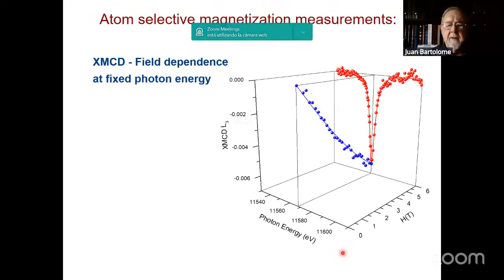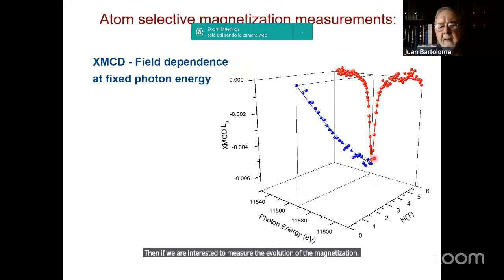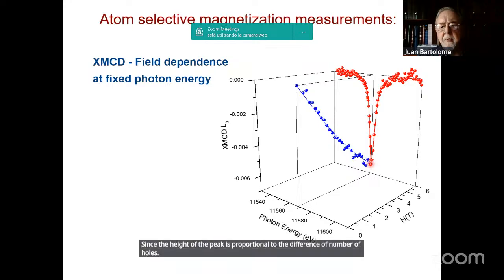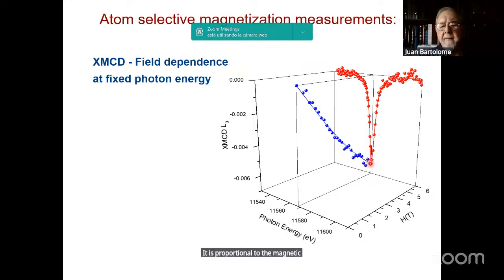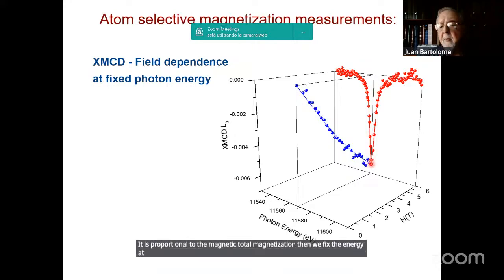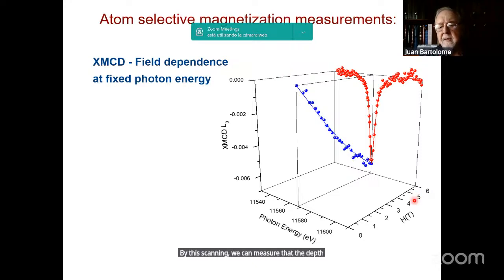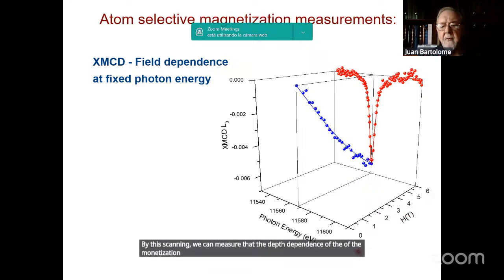So then, if we are interested to measure the evolution of the magnetization, since the height of the peak is proportional to the difference of number of holes, it is proportional to the total magnetization. Then we fix the energy at one value of the minimum or a maximum in the XMCD signal, and then we performed different experiments at different fields. By this scanning, we can measure the dependence of the magnetization as a function of field.